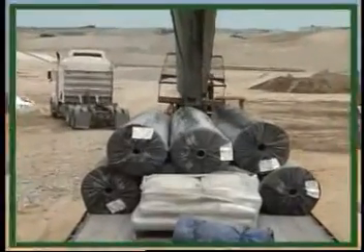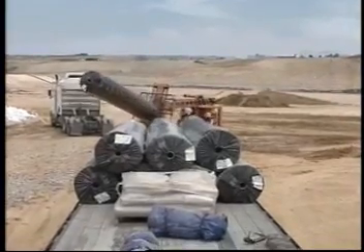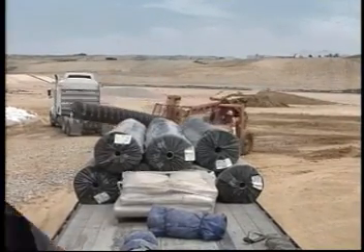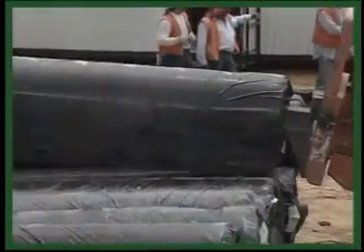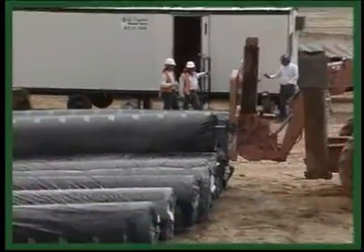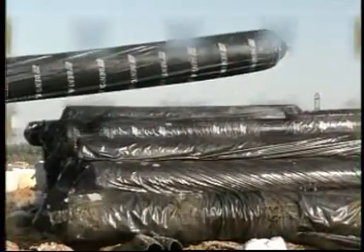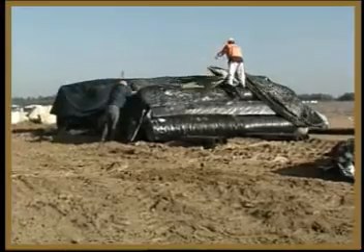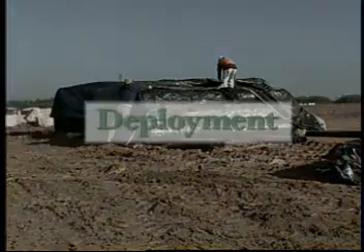Contact CETCO for specific information regarding the size and strength requirements of the various types of unloading equipment. As you're unloading, each roll should be inspected for damage. GCL rolls should be stockpiled in a level, dry, and well-drained location, away from construction traffic. Keep the stack height no higher than 4 rolls, and cover the stack with plastic sheeting for additional protection.